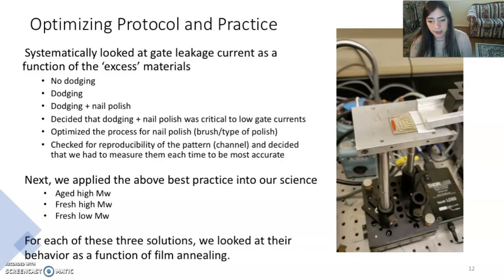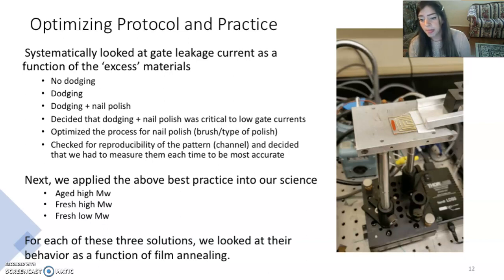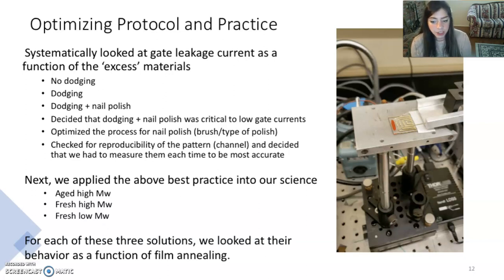To identify which methods and materials result in the highest performance, a series of experiments were conducted. We systematically looked at gate leakage as a function of excess materials. We used the term 'dodging,' which basically means scraping away extra substrate to isolate the channels and increase chip performance. The addition of nail polish is just one extra step to ensure the isolation.